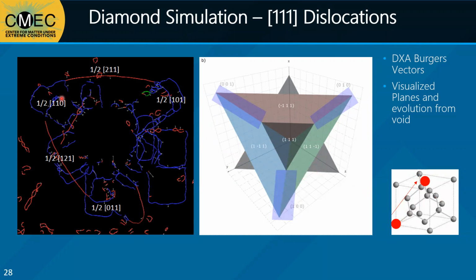This dislocation can also be understood as the sum of these two rectangular bands here, the 1/2 110 and the 1/2 101, which sum together to be the 1/2 211. It is believed that there might be some kind of reaction occurring between these two dislocations that causes this half loop to form between them. But still, we don't know exactly why this third half loop is not connecting these last two rectangular bands.